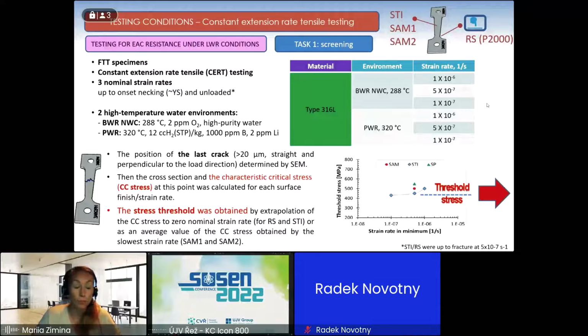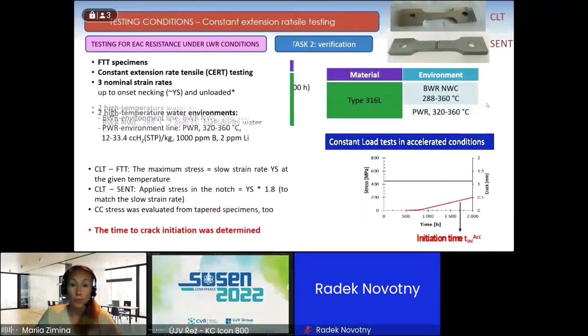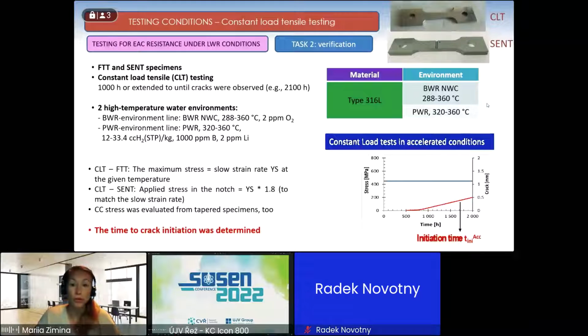Then we assessed the cross section and determined the characteristic critical stress for each surface finish, and for each strain rate. And then using this data, the stress threshold was obtained by extrapolation of this characteristic critical stress to 0 nominal strain rate. And by obtaining this stress threshold, we were able to set the parameters to the second task, which was the verification task using constant load tensile testing for this crack initiation testing.